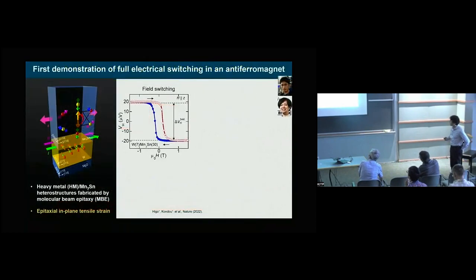And here comes the highlight of this work. So we send electrical current through this. There's tungsten, this is a heavy metal, and it induces a spin Hall effect. And the spin accumulation actually is sent into this, and the spin current polarized along the perpendicular direction to the Kagome was introduced, to see whether this actually flips in terms of 180 degrees, so the octopolar direction, if you like, from up to down. And if this works, you should be able to see the sign change of the Hall effect with the same amplitude as in the case of the magnetic field control. And this is one example of the field control of the Hall effect using such a device.